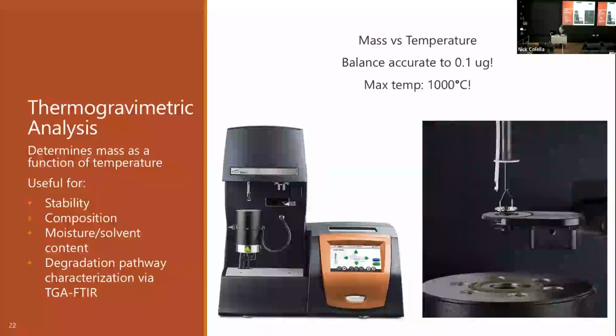So heating can, again, cause degradation. It can cause evaporation. So if you want to, you can burn off organic content and leave the inorganic content. So if you have, say, inorganic nanoparticles in an organic matrix, you can burn off the organic matrix, see how much mass is left behind, and that's the percentage that was organic to begin with. So it's a really nice way to quantify composition if you have a mixture of materials.